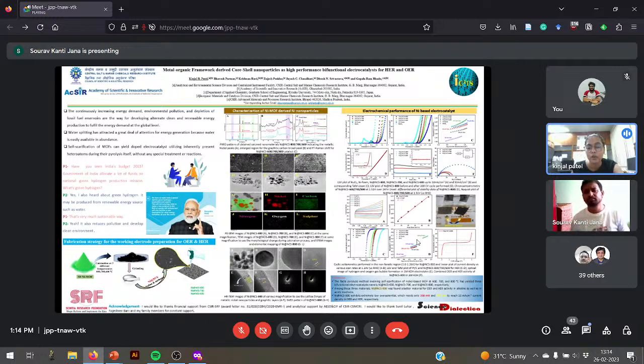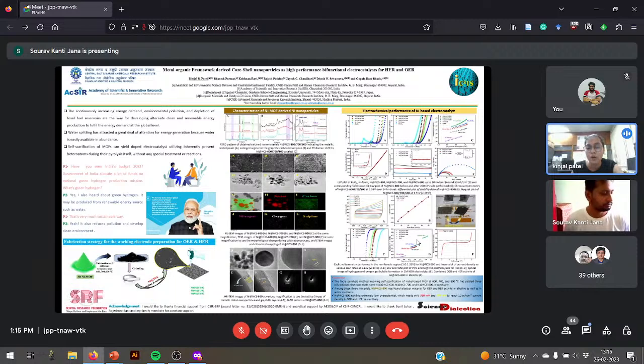And for the overall water splitting, we also use the hydrogen evolution reaction using linear sweep voltammetry. The catalyst obtained at 800 degrees Celsius shows the lower potential, which is 366 millivolt, and the Tafel parameter has also been evaluated. For the overall electrochemical water splitting, we have also used a two-electrode system where bubble formation takes place at the anode and cathode. So here I would like to conclude that the catalyst obtained at 800 degrees shows better electrochemical activity towards the hydrogen evolution reaction and oxygen evolution reaction.